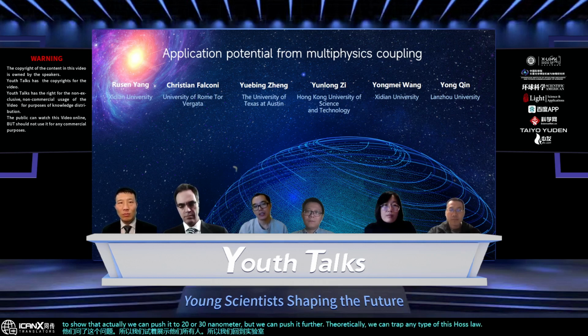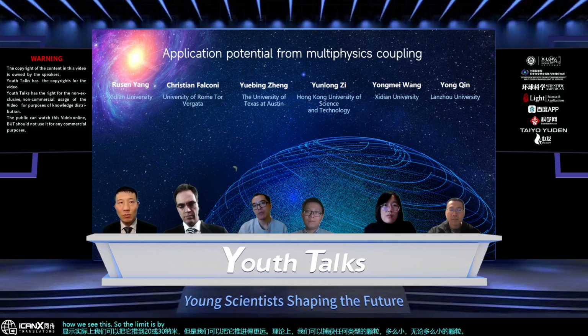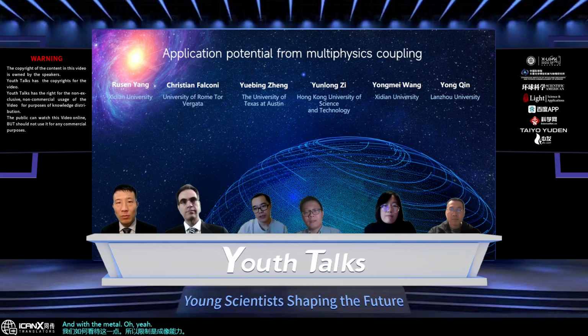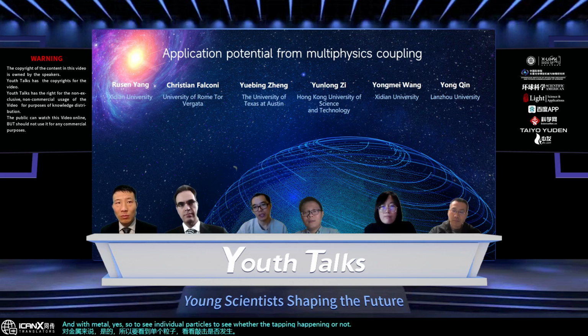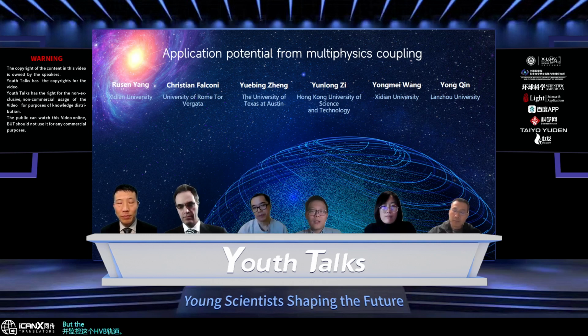But the challenge is how we see these. So the limit is by the imaging capability. To see individual particles, to see whether the trapping is happening or not, we need to monitor where the particle is, and to monitor whether it is actually trapped. But the imaging capability limit is hundreds of nanometers if you are using visible light.